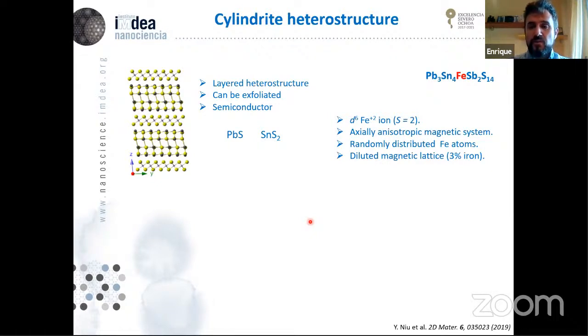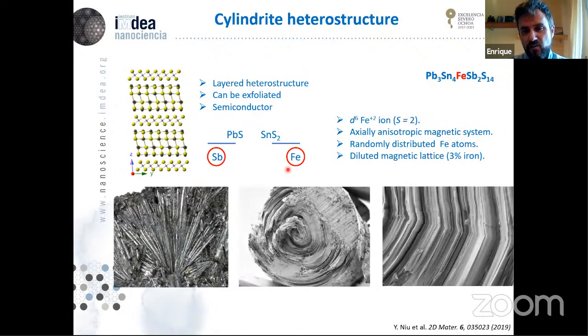But for that, we were wondering what happens if instead of using molecules, we use other low-dimensional materials that also have this spin. So for that, in collaboration with Andres Castellanos and Mar Garcia at the ICMM, we have studied this material, the Cylindrite. The nice thing is that this is a layered heterostructure that can be exfoliated and that has 3% of iron atoms in the lattice. So we could be using those iron atoms as well as potential qubits.